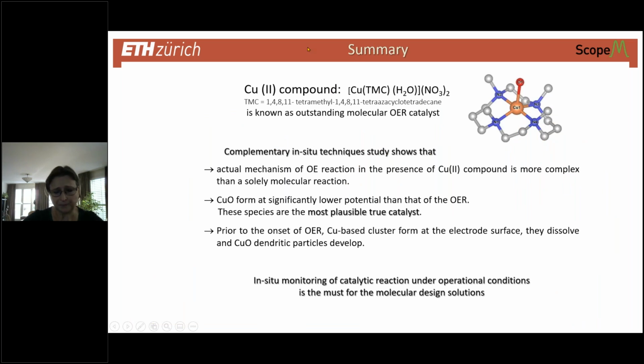And now it's our summary, based on the before and after studies. The copper-2 compound, known as an outstanding molecular oxygen evolution reaction catalyst, is studied by a number of techniques, and we showed that the actual mechanism of the oxygen evolution reaction in the presence of this compound is more complex than the solely molecular path. First, we have copper-containing particles forming at the electrode, then they dissolve. At the later stages, copper oxide particles or dendrites form, still at a much lower potential than that of the oxygen evolution reaction of the same compound. This we consider the most plausible true catalyst of the reaction.